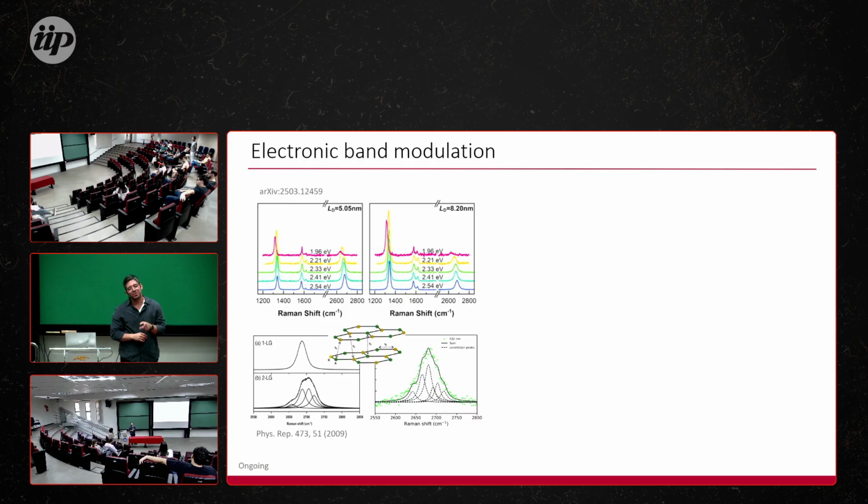However, CVD is not so good sometimes when you're doing this kind of measurement, because it's easier to go to lower temperature, like 4K or something like that. When you decrease the temperature, the excitons' peaks start to be sharper, right? However, sometimes you see a lot of features that could come from something we didn't know was there, because of the deposition during the growth. So sometimes it's a little bit more tricky.